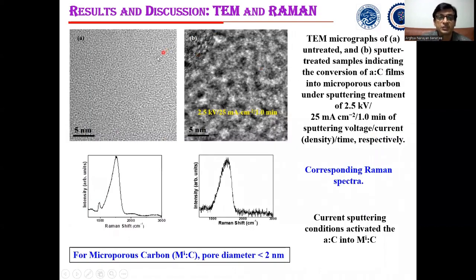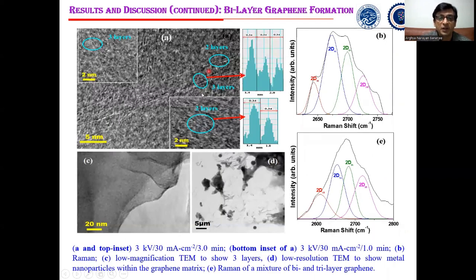Now, these are some results and discussions, some TEM and Raman images of the amorphous carbon, and we can see the TEM image of some microporous carbon before graphitization using some low sputtering parameters. And this is showing the typical Raman spectra of an amorphous carbon and microporous carbon, which is only showing a small D peak, which is typical of an amorphous carbon network. Now, when we increase the sputtering parameters, we were able to fabricate some graphene layers on this microporous carbon network. You can clearly see some bilayer or trilayer graphene formation in the graphitic microporous network.